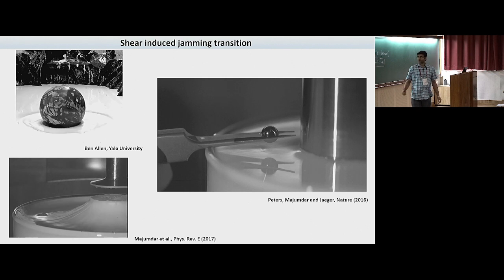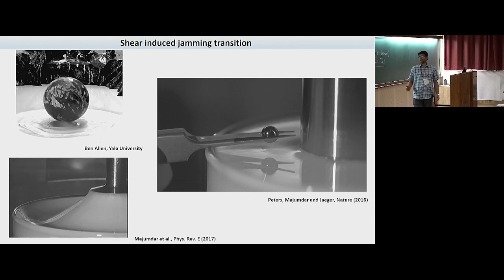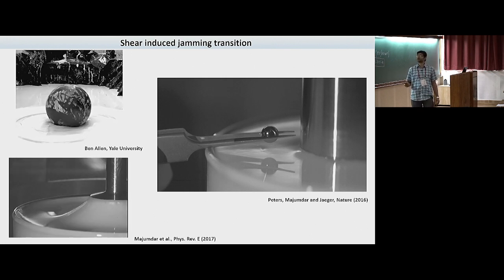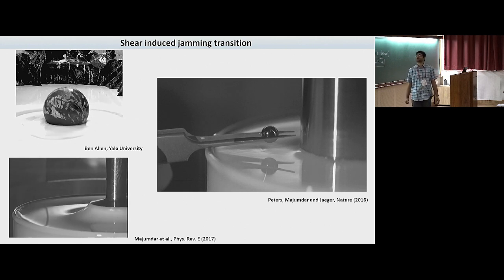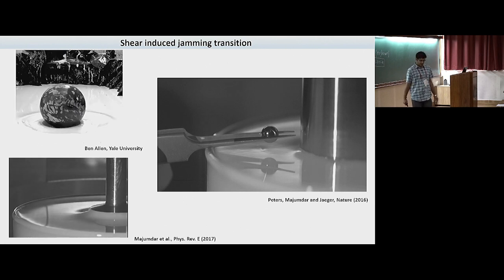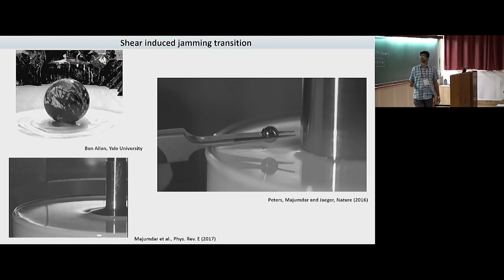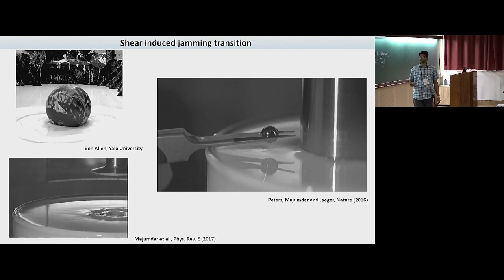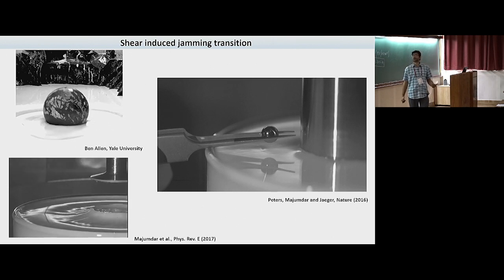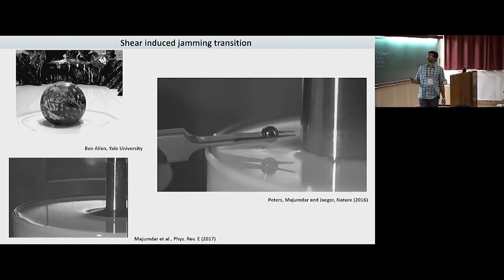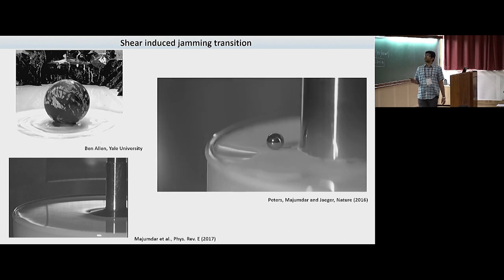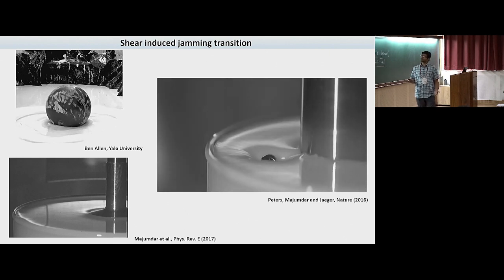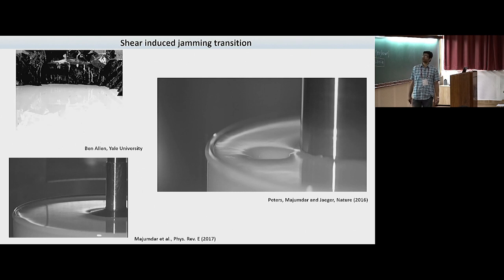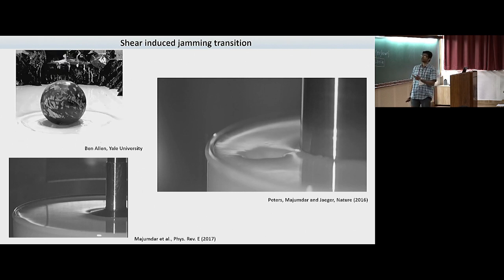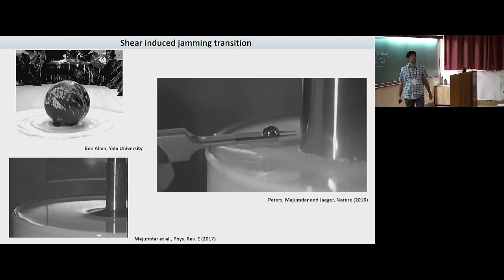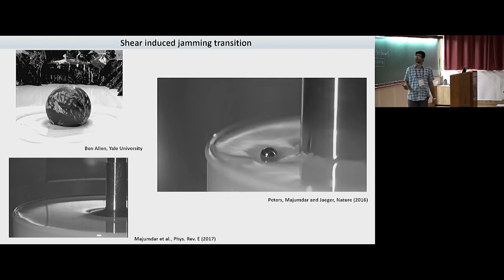Such force-induced changes can occur under any kind of force, like compressive force or extensile force. Basically, the origin of this effect is that all these deformation modes are linked to shear deformation. You can see that if we shear the suspension, it solidifies, and if you stop shearing, it goes back to the initial liquid-like state. This is a dense suspension of cornstarch particles in water.